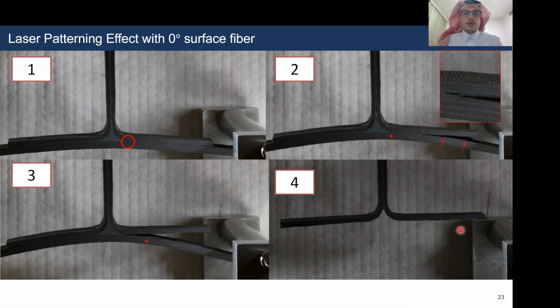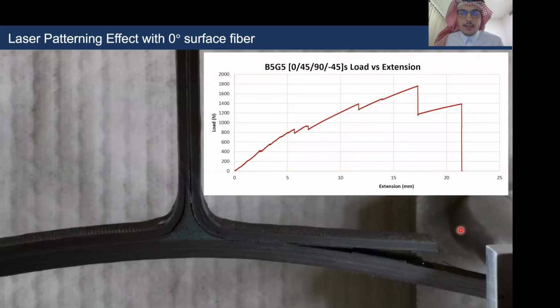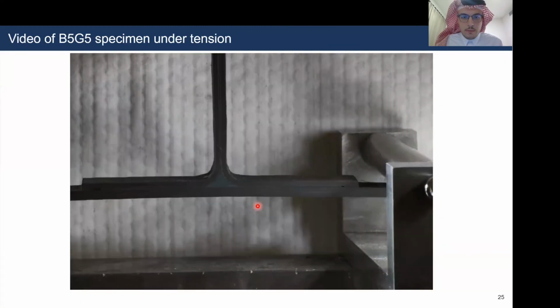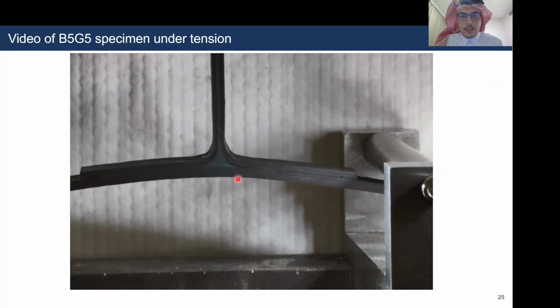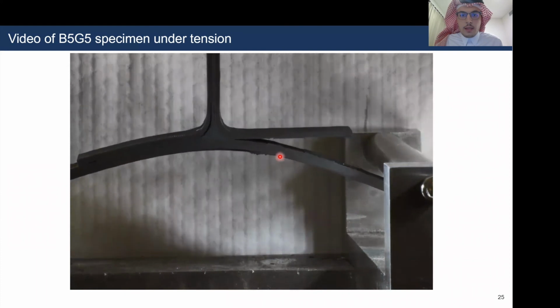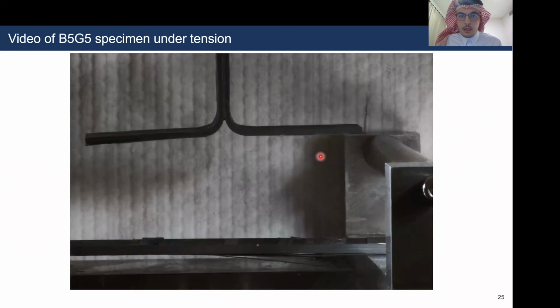So to relate those adhesive ligaments to the load extension curve which resulted for the specimen, we can relate each adhesive ligament with a peak drop. Or if I may say, we can relate it with an enhanced toughness, an increase in the extension of the T-joint. There have been 4 adhesive ligaments, as I said, and when the fourth one failed, the sudden failure happened. So we can look at this video here. We can see that the adhesive ligaments first initiated here, then at the edges. And then when the adhesive ligaments were completely failed, sudden failure happened. Let me play the video one more time.